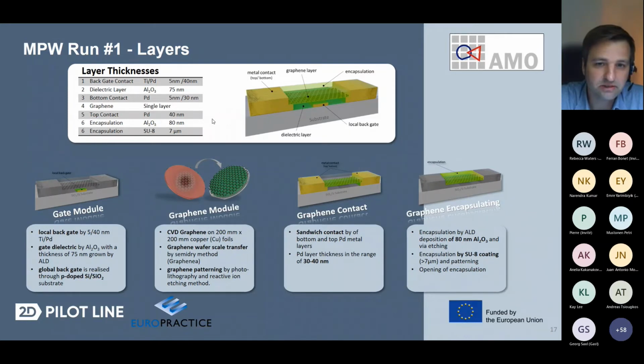The layer thicknesses of these devices are summarized here in this table. So we have in total 6 layers, as mentioned, starting with the backgate contact with a thickness of 40 nanometers, and we use palladium here. It's followed by a gate dielectric of aluminum oxide with a thickness of 75 nanometers. And optionally, you can of course leave this gate contact away. Then you still would have the possibility to gate your device through the global silicon substrate.